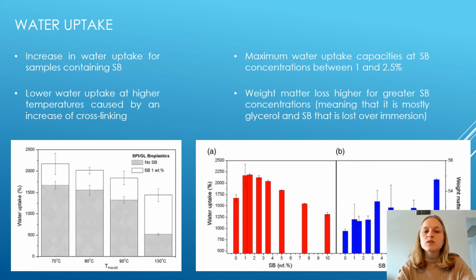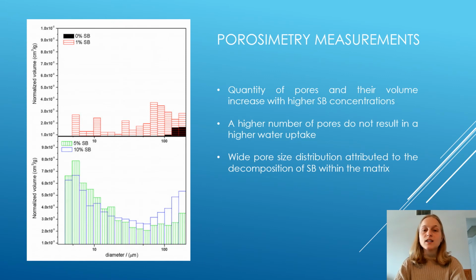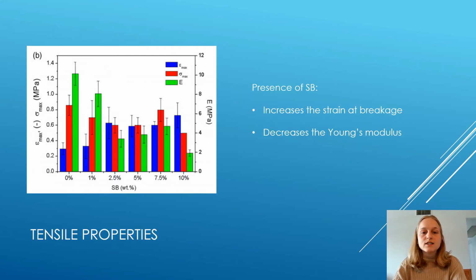This could be caused by the reduced amount of protein available or the reduction of elongation properties at higher SB contents. In addition, wider pore sizes have been detected in materials containing more SB. As we can see, the volume and number of pores increase with the higher values of SB, contrarily to the water uptake. This means that they are not related, as neither the entrance or exit of water would be favored in the samples. The presence of SB also impacts the tensile properties. As we can see, an increase in SB results in the material being more easily deformed with a lower Young's modulus and a higher strain at breakage.